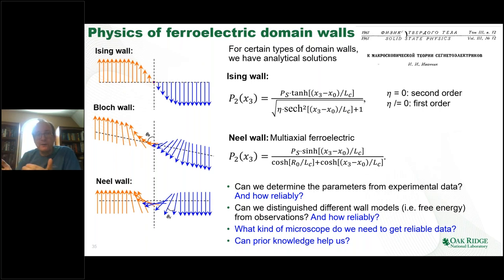Again, let's go back to the ferroelectric materials. A ferroelectric material has an order parameter, which is polarization. And it turns out that for a vector order parameter, we can have three types of domain walls. The Ising wall, when the polarization goes down, disappears, and then reappears with the opposite sign. The Bloch wall, when it rotates in plane. And the Néel wall, when it rotates, as shown on this image.